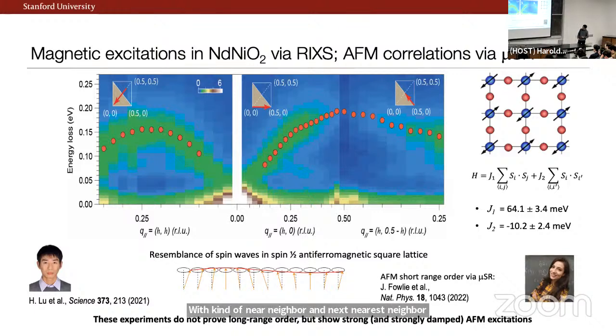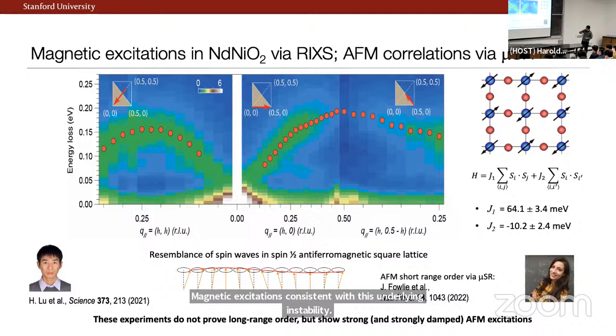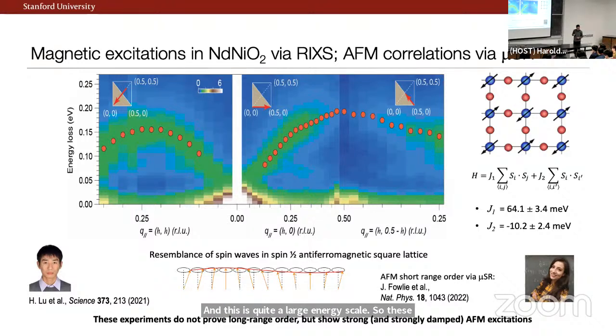We also studied for these antiferromagnetic correlations by using muon spin rotation. So the details aside, I should emphasize we did not prove, nor do we have evidence that there's static long-range order, that we have this formal ordered antiferromagnetic phase. But what we did find is very strong and strongly damped magnetic excitations consistent with this underlying instability. Right? And this is quite a large energy scale. So these magnetic excitations extend up to 200 millielectron volts. So it's quite a large energy scale that some people are thinking might be relevant for providing the coupling relevant for superconductivity in the system.